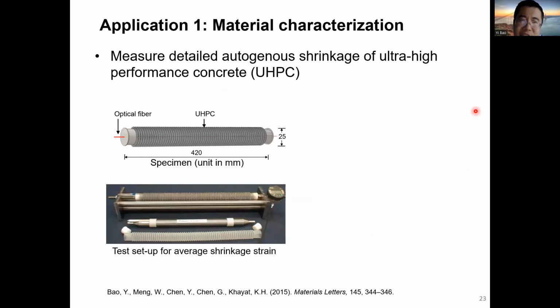So this slide shows an example for the material characterization. We use the fiber optic sensor to characterize the autogenous shrinkage for ultra-high performance concrete. As you know, the shrinkage of concrete could cause a lot of problems, such as the early degradation of structures. According to ASTM standard, the autogenous shrinkage of mortar can be measured using a corrugated tube, and we could measure the length change of this tube over time.